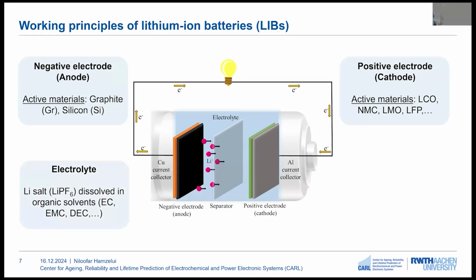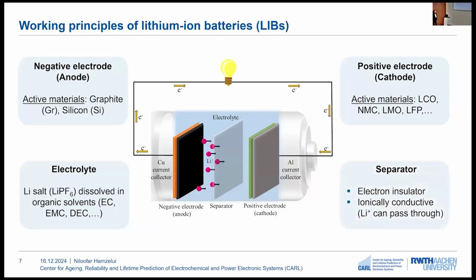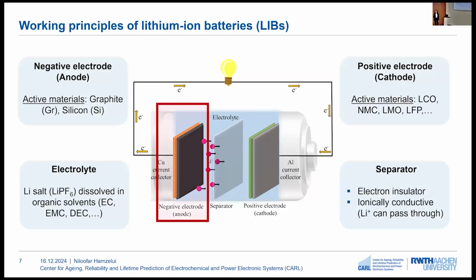We also have the electrolyte within the lithium-ion battery, so the electrolyte can come in different shapes like the liquid electrolyte, polymer electrolyte, or solid electrolyte. In this work, liquid electrolyte has been used, which usually consists of a lithium salt such as LiPF6 dissolved in some organic solvents such as ethylene carbonate, ethyl methyl carbonate, and so on. And then in between the electrodes, we have the separator. The separator is electronically insulating and ionically conductive. In this work, the main focus will be on the negative electrode or the anode of the lithium-ion battery.